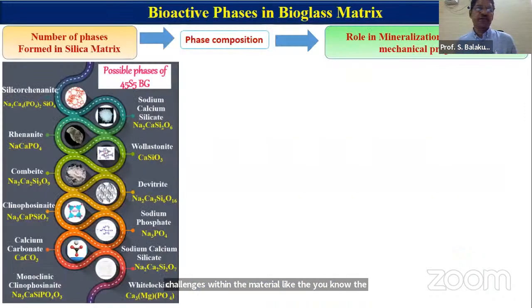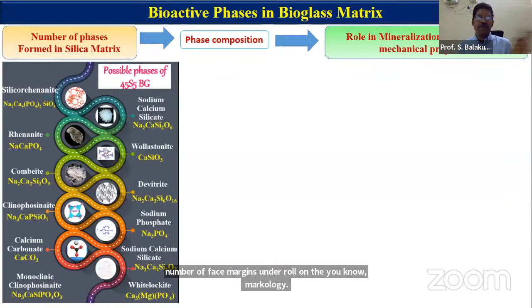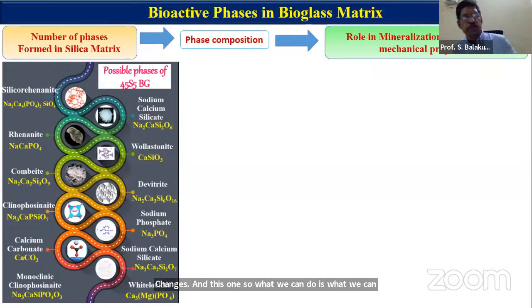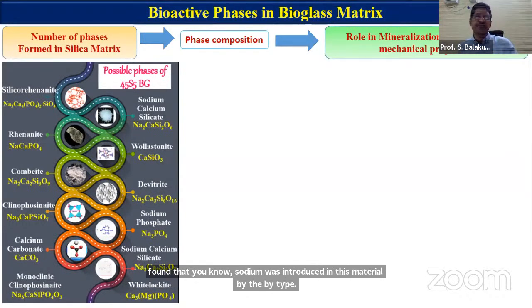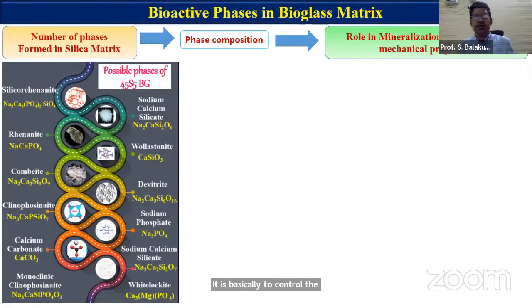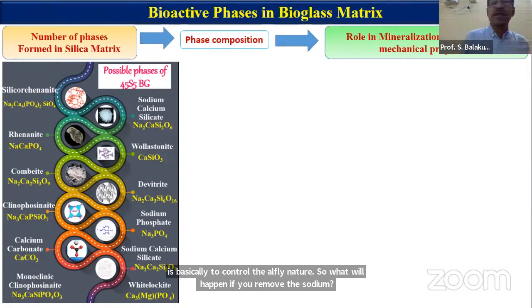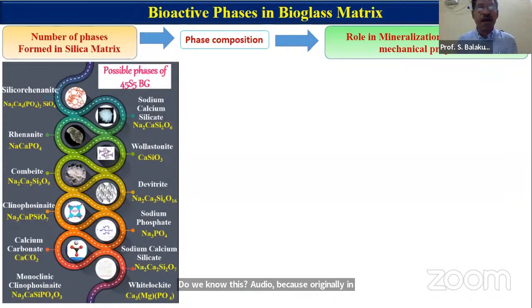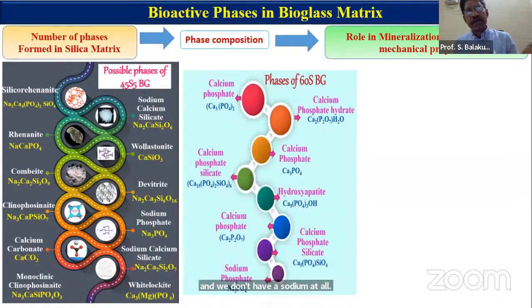But obviously, if you look at the entire literature, they are talking about the technological issues, but not much about the challenges within the material, like the number of phases and their role in the morphology changes. What we found is that sodium was introduced in this material by Hench. It is basically to control the alkaline nature. So what will happen if you remove the sodium? Originally in our bone and teeth we don't have sodium at all. So that is why we modified it.